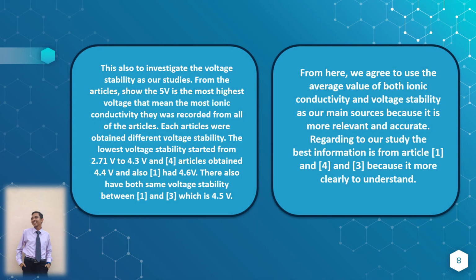This also investigates the voltage stability in our studies. From the articles, 5 volt is the highest voltage recorded for all of the articles. Each article obtains different voltage stability. The lowest voltage stability ranged from 2.71 volt to 4.3 volt, and 4 articles obtained 4.4 volt, and also one article had 4.6 volt. Articles 1 and 3 also have the same voltage stability, which is 4.5 volt.